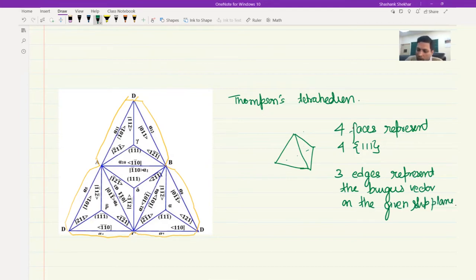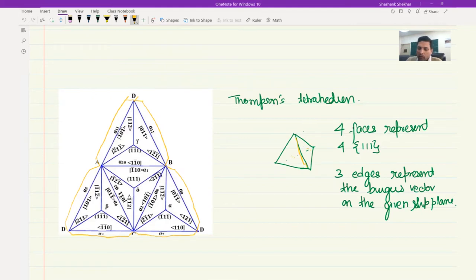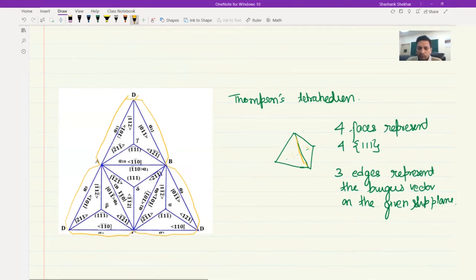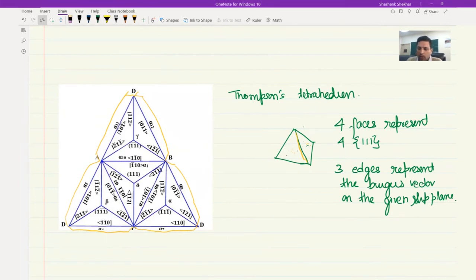Clearly from this, if you take a particular edge which is shared between two planes, that particular Burgers vector is common to both of those planes. It also tells you a lot about dislocations. If you have a screw dislocation with this Burgers vector, then the screw dislocation line vector is also along this direction, and therefore it can cross slip into either of those planes. So if it is moving on one plane, it can also move into the other plane.